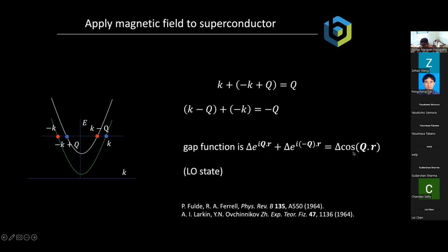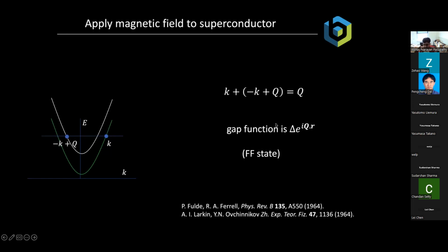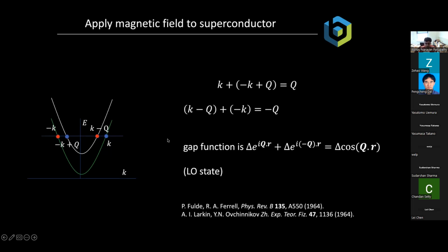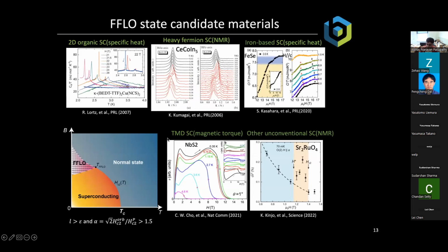So in the LO state, the superconducting order parameter looks like a real number, but the magnitude of that superconducting order parameter is changing in space. It's moving sinusoidally or cosinusoidally. Whereas in the other state, this FF state, the amplitude of the superconducting order parameter is a constant in space, but the phase of the superconductor is winding in space in equilibrium. So I don't have to apply a voltage to the superconductor to make this happen. It's just in equilibrium, this would happen. And collectively, these two states, people call them the FFLO state. And there has been a lot of beautiful work done to try to look for evidence of this FFLO state in a number of different materials at high magnetic field.